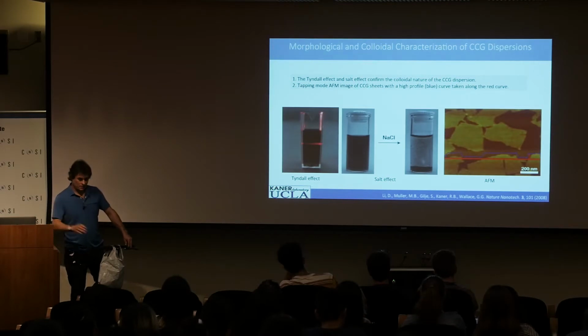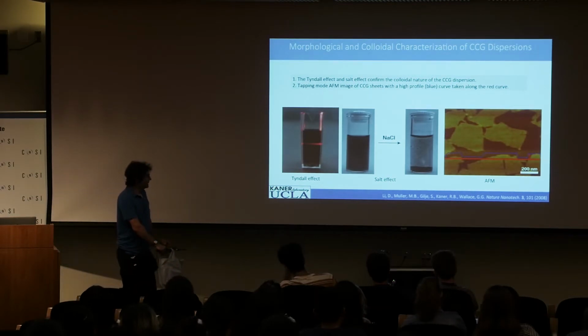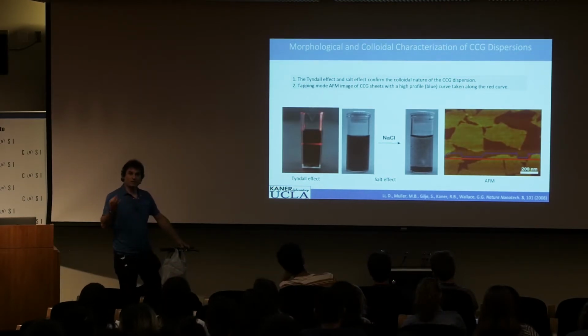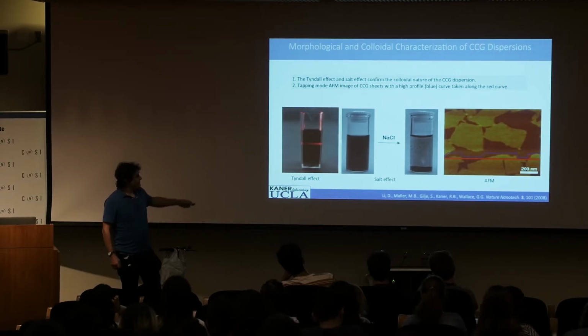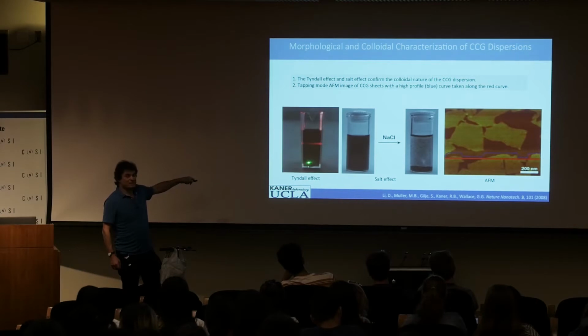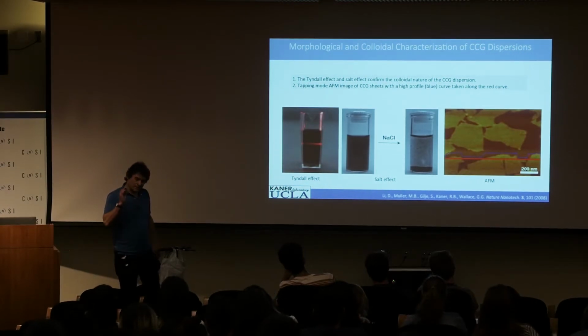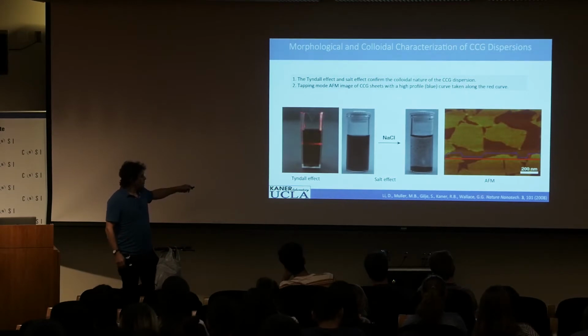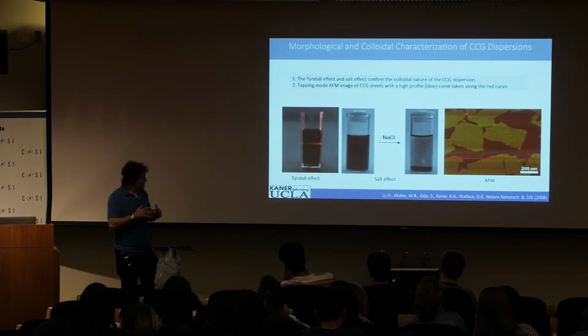So first, I'm going to tell you a little bit more about graphene oxide. The first thing we did as chemists, we hit it with hydrazine, N2H4, which is a good reducing agent. And when we did that, this is the reduced form. It still disperses in water and shows what's called the Tyndall effect. So the Tyndall effect is, if this were a solution, a laser would go right through it. But you'll notice the laser is being scattered. It's being scattered because you have individual sheets of this chemically reduced graphene oxide. So we have graphene sheets.